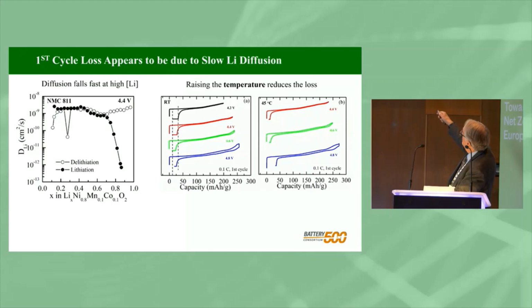So what we've done here is charge them up, discharge it to 2.8 volts, then hold this for about 4 hours so you can see more lithium gets in if we just hold it there. Again, indicative of kinetic control. So if we now raise the temperature from about 21 to 45, you can see here, this gap here is much smaller than in this case, same here. So again, indication of kinetic control. Now you see at 4.6 volts that we're getting separation. So at 45 degrees, we've got more reaction going on with the surface. So this is always a problem with these materials, the compatibility with the surface of the material and the electrolyte.